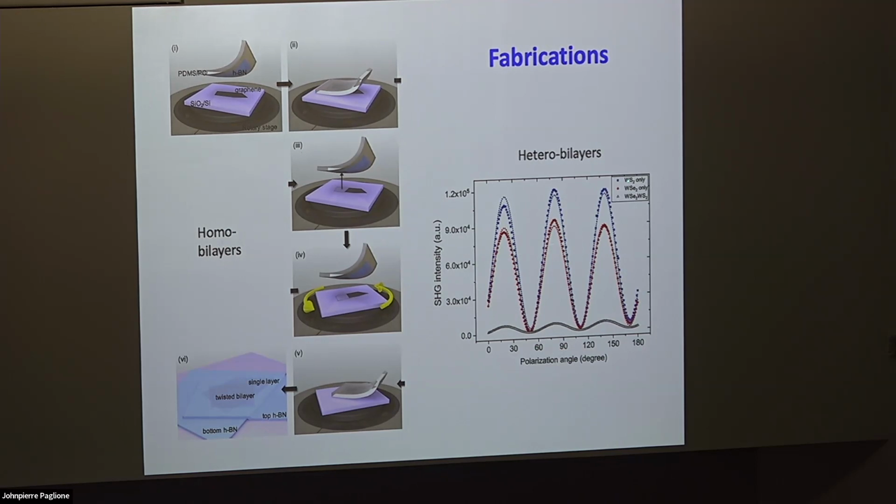So you will just do this for each of the films. For instance, the blue dots are for the tungsten sulfide film, and the red dots are for the tungsten selenide film. And before you align them, of course, this periodic pattern, they don't really align on top of each other, right? So you do the crystallographic orientation, then you align them. Now they're nicely lined up on each other. And then you know the crystallographic orientation, you put them on together. And now you can generate the Moiré heterostructure in this way for the heterobilayer.